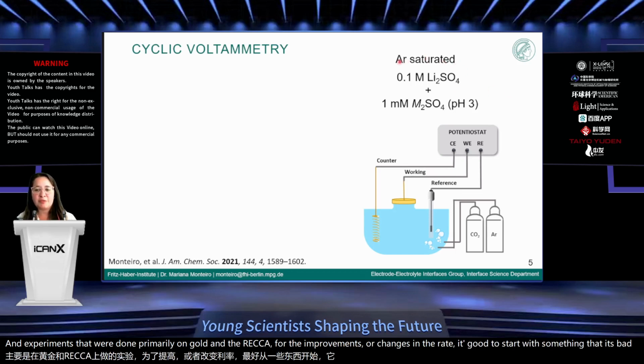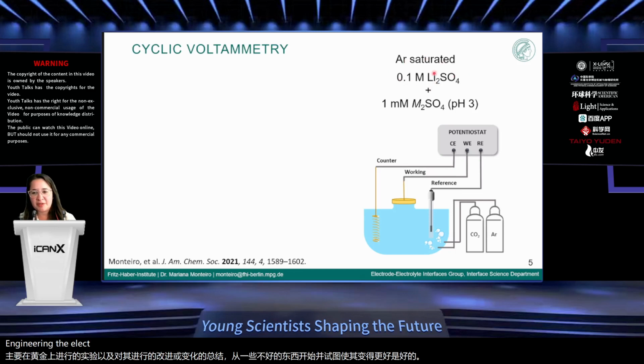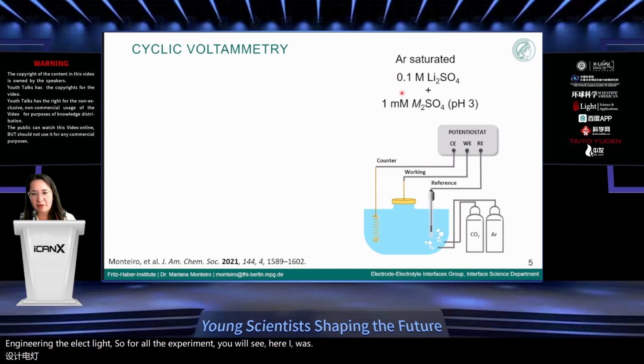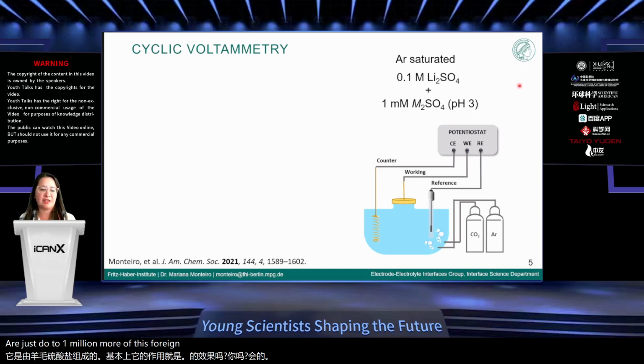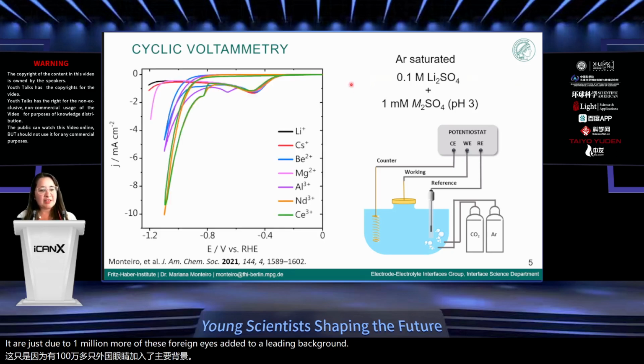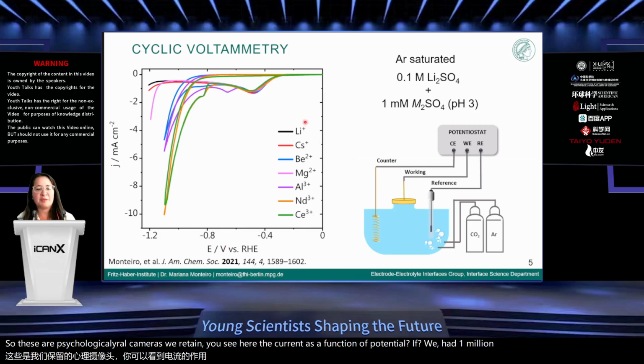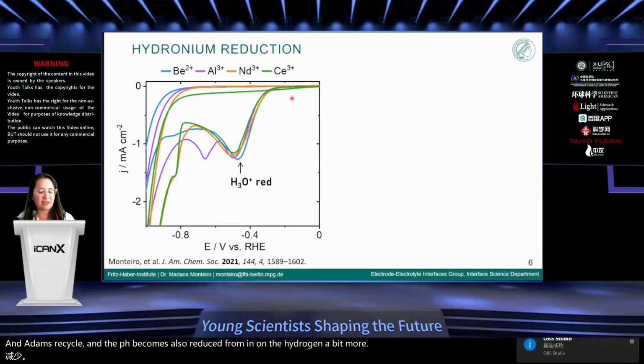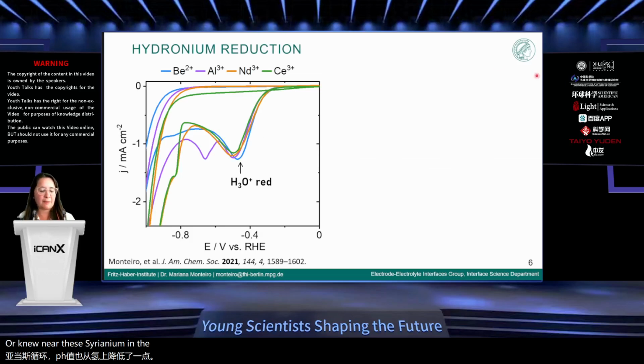So for all the experiments you will see here, I was using a background electrolyte composed of lithium sulfate. Basically, all the effects you will see are just due to 1 millimolar of these foreign ions added to a lithium background. These are the cyclic voltammograms we obtain, showing the current as a function of potential. If we add 1 millimolar of all these different species, the solution does not really affect hydronium reduction a lot,